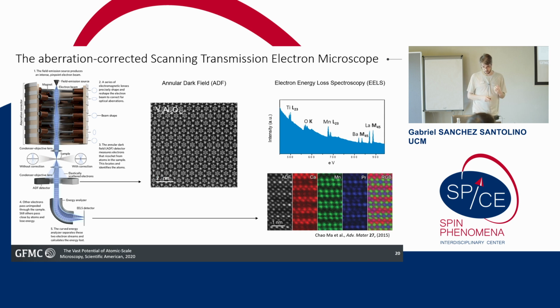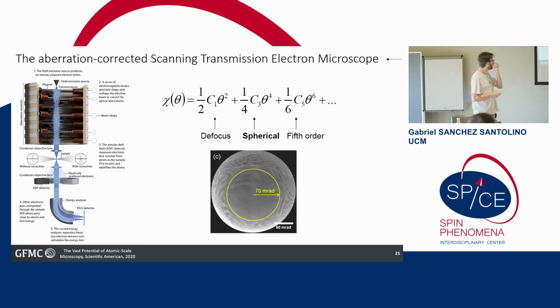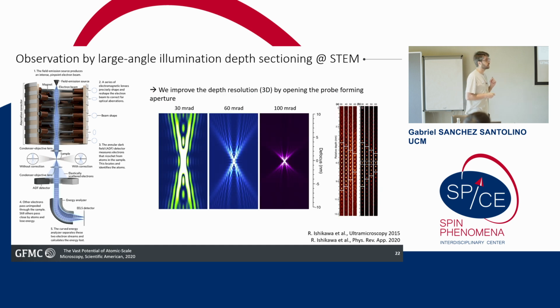And this is very important for this work, because one of the things that we can do with this is open the aperture that we use to form the probe of our microscope. So this is the aberration function. This angle here is the angle from the optical axis to the edge of the aperture that we use to form the probe. If we open the aperture more, we are going to have a more convergent beam, and having a more convergent beam, we are going to improve the resolution in the three-dimensional direction.